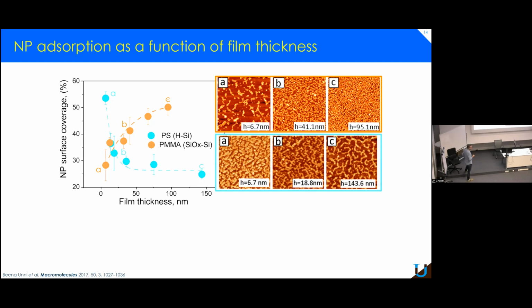adsorption, the coverage of the nanoparticle actually varies exactly in the same way as the ellipsometry measurement that we showed before. Here you see the polystyrene. So when the thickness is very small, the amount of nanoparticle is very high. It's getting higher and higher. And for the PMMA, it's exactly the contrary. So you can imagine that here, PMMA should have a refractive index that actually decreases with the thickness.